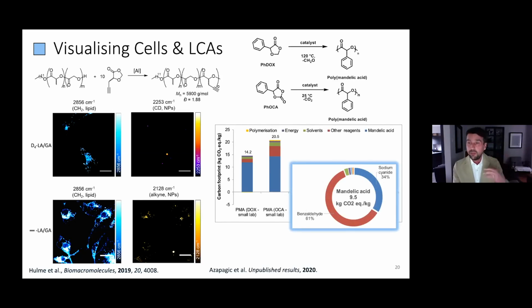And finally, I want to come back to this idea of sustainability, right? I've been harping on about how, look at us, we can make polymandelic acid. We wanted to make sure that that was a good thing to do. So we wanted to compare this phenyl DOX system that we have to make polymandelic acid to the traditional or best practice phenyl OCA-based system. I can do an LCA with our collaborators, this is Adisa Azapagic in Manchester, and see what a good drop-off we have: 20.5 kilograms of CO2 per kilogram down to 14.2. So a big savings there.